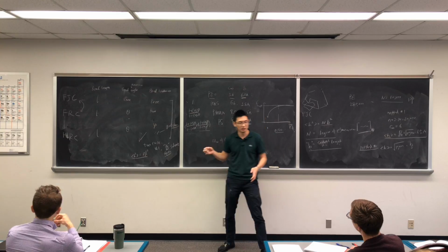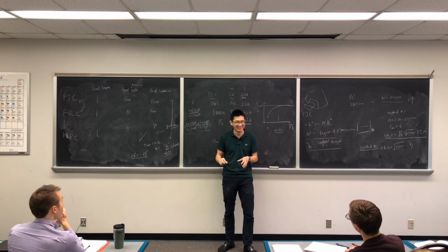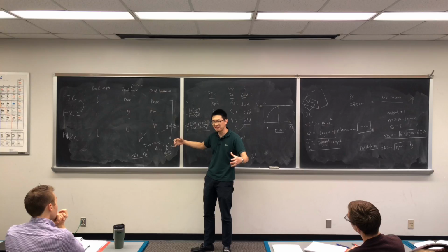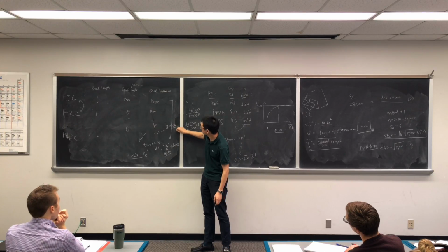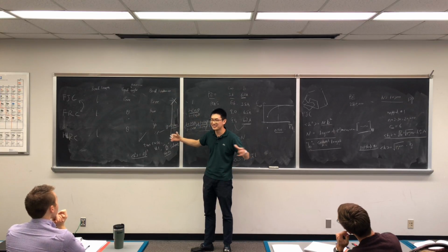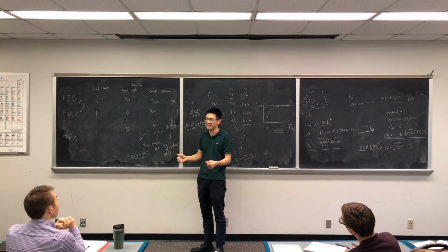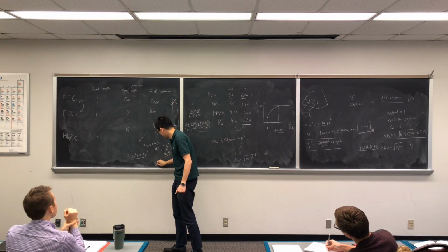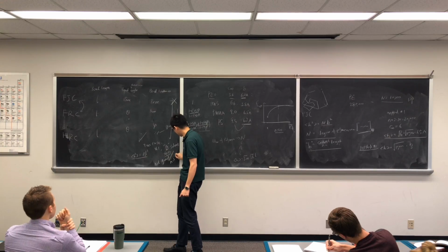Okay, so if you keep adding bad solvent to your polymer, there will be a time your polymer will start to shrink little by little, right? Because it's a bad solvent and doesn't want to expand. It will pass this point in terms of coil size, then we stop there. We call it theta solvent condition. So in a nutshell, theta solvent is not a good solvent, but neither a bad solvent.